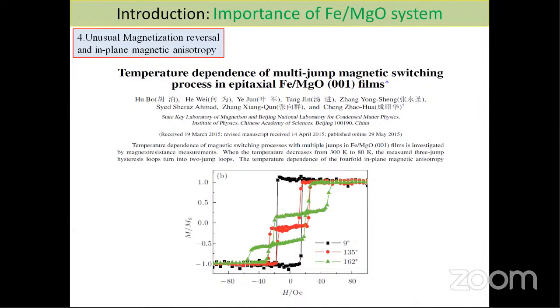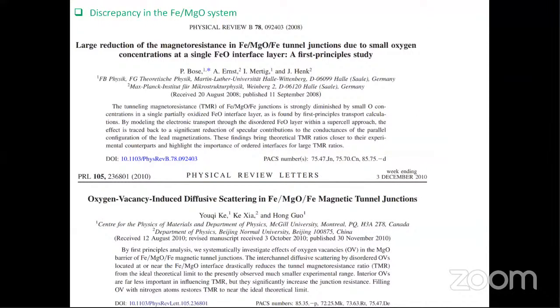The Fe/MgO system is also debatable because of the formation of oxide at the interface during the growth of Fe on MgO. Some report the formation of oxide in a few layers of Fe at the Fe/MgO interface, and some other reports say that there is no formation of oxide during growth of Fe on MgO. So my objective is to study whether oxide is formed or not at the Fe/MgO interface on ion beam cleaned MgO substrate. For this, we have used our in situ ultra high vacuum chamber, which has the following capabilities.